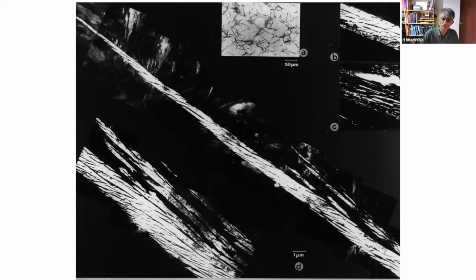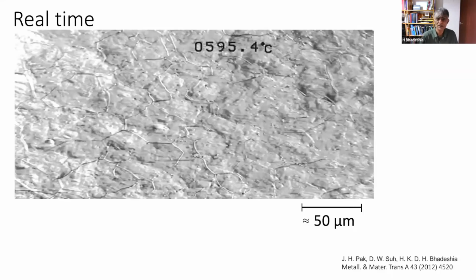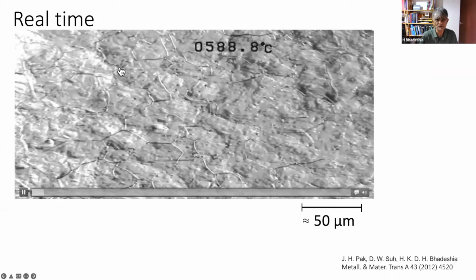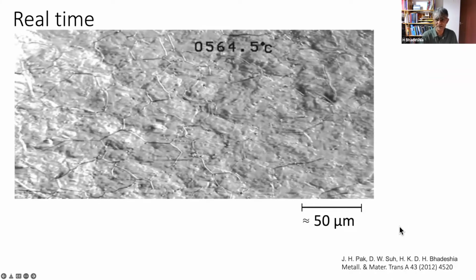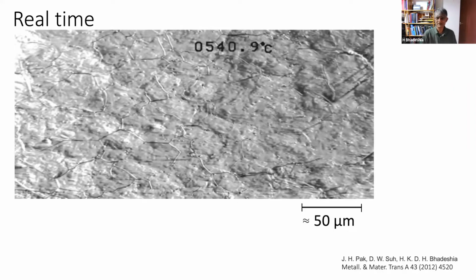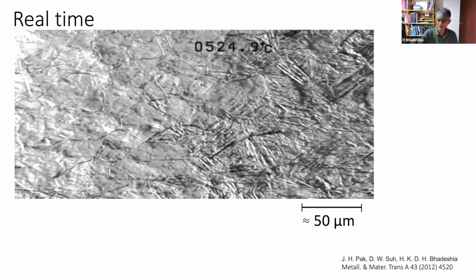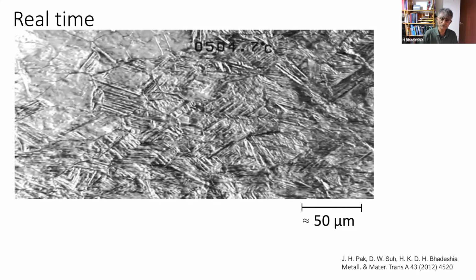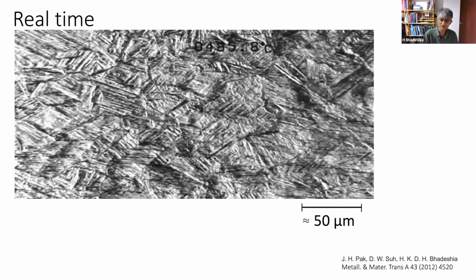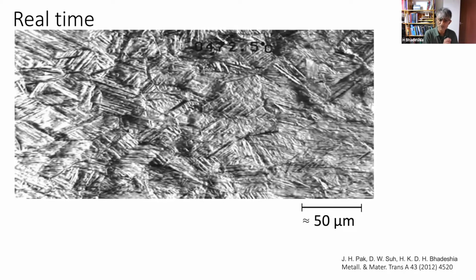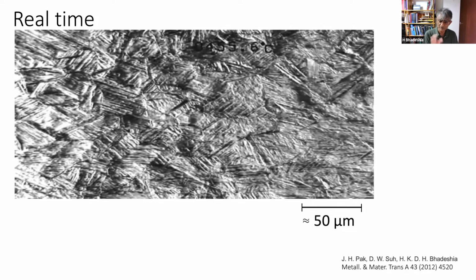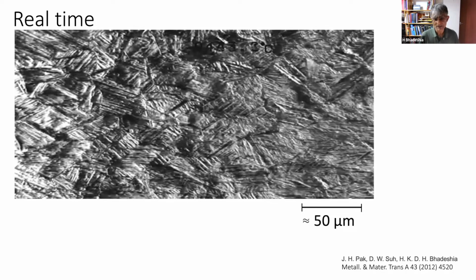So let me first of all show you that this actually results in a shape deformation of the type I described for a displacive transformation. So this is a sample which has been polished optically flat, and we are allowing it to transform to bainite. And you can see that you produce these surface upheavals, which I will show you in the next slide, correspond accurately to the shape change that I described earlier. So this is a real deformation. These transformations not only change the crystal structure, but they also have a physical deformation associated with them.